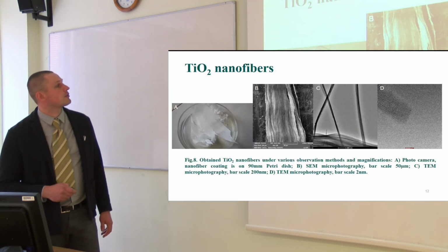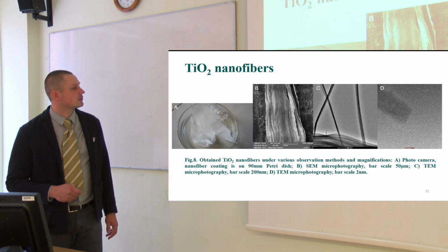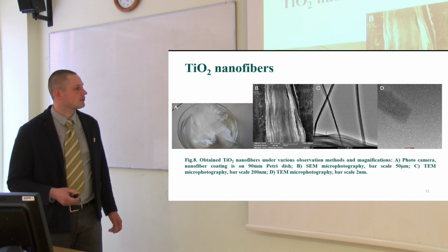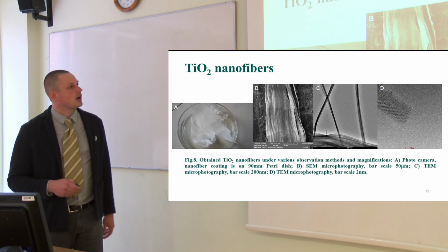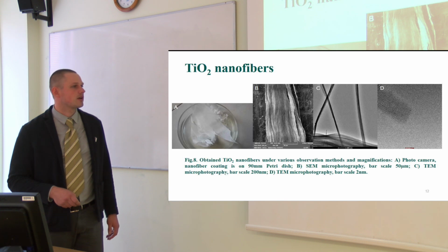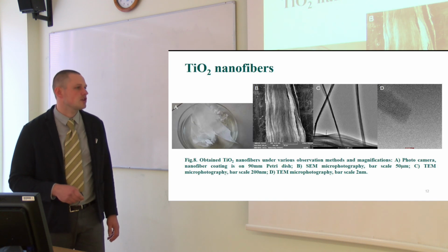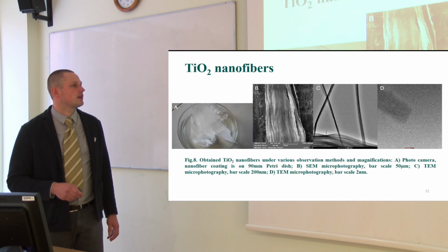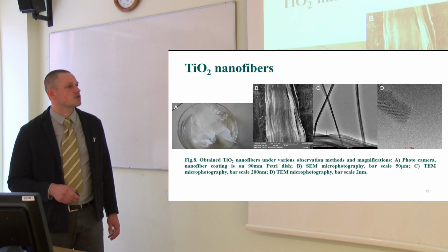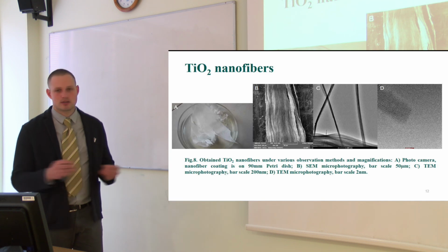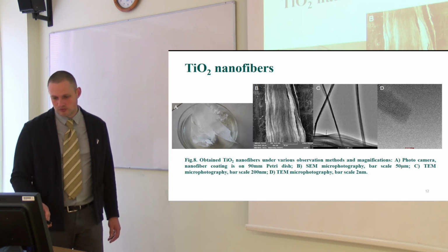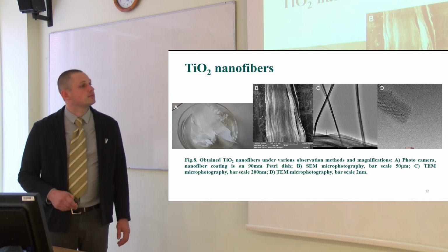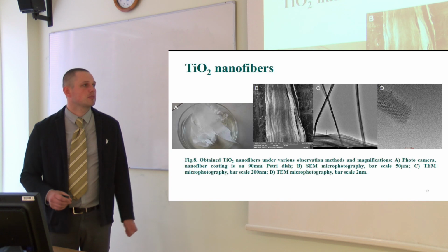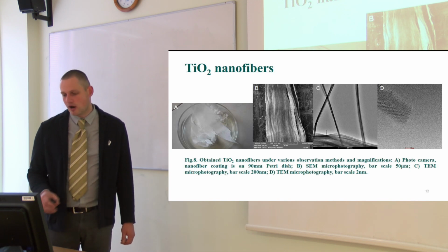Here you can see obtained nanofibers. This is a petri dish where we can put the nanofibers on it, and those pictures are already under huge magnification in scanning electron microscope and in transmission electron microscope. As you can see, we have good orientation of those nanofibers, and single nanofiber can have a diameter starting from 5 nanometers.